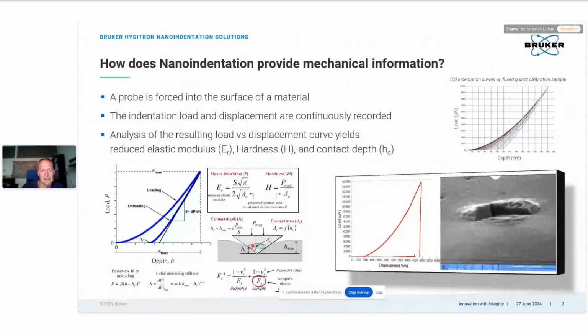Our tip and the geometry of the tip is very well calibrated on a standard material of fused quartz. So we do a lot of indents at different depths. And since we know the mechanical properties of this standard, so we know the elastic reduced modulus, we can calculate what is the contact area needed to get these reduced elastic modulus values. And that's the way we can construct the so-called tip area function, which is a function of the contact area with the contact depths.